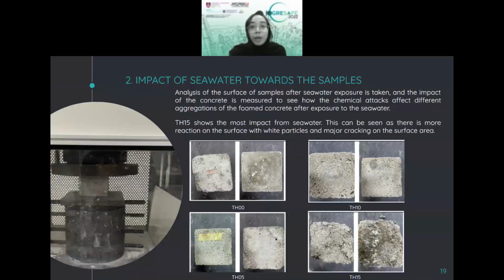So analyzing the impact of seawater towards the sample. Here are some of the pictures I took of the surfaces. This can show the before and the after when I submerged the concrete into the seawater. The analysis of the surface of concrete exposed to seawater shows some differences due to the chemical attack. But based on my analysis, TH15, where I use 15% of the timber husk inside the foam, shows a very obvious reaction towards seawater. And TH5 and TH10, where I use 5% and 10% of timber husk, show at least a little cracking and white deposits from the seawater.